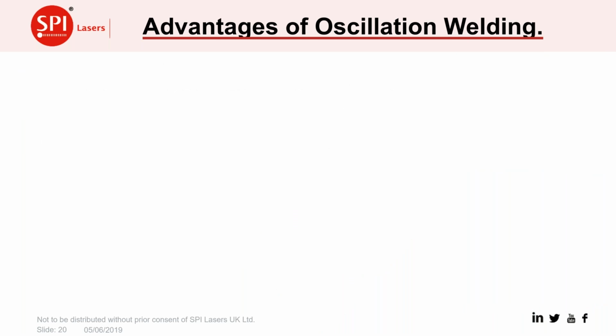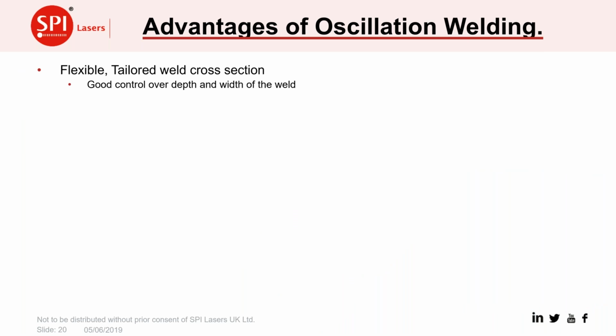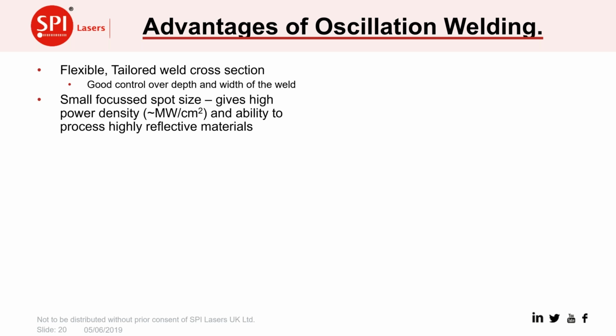That's generally what oscillation welding is, and why do we want to use it? The first reason is that we can produce a flexible or tailored weld cross section. By using a combination of the parameters, we can have good control over both the depth and the width of the weld in a way that we can't do with normal welding applications. Because we can produce even a wide weld with a small focus spot size, and the small spot size gives us a high power density, we can actually use this process on highly reflective materials such as aluminium and copper, which we'll have a look at in a bit.